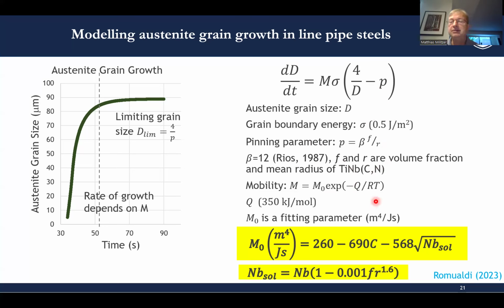The mobility depends on temperature. One assumes typically an Arrhenius behavior for these line pipe steels. It had been shown that the apparent activation energy of 350 kilojoule per mole is a reasonable assumption. And then we have just the pre-exponential term as a fitting parameter. And we found that the mobility, the apparent mobility, decreases with adding carbon and with niobium in solution. So niobium in solution, that's consistent with our DFT analysis, showing niobium as a strong segregating element.